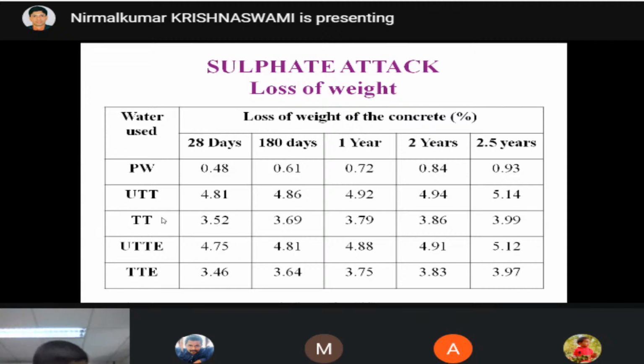Then coming to the treated tannery effluent, it is 3.52% for 28 days, and for 2.5 years it is 3.99. And for untreated textile effluent, it is 4.75 for 28 days, and it is 5.12 for 2.5 years. And for treated textile effluent, it is 3.46 for 28 days and 3.97% for 2.5 years. This is the loss of weight of concrete.